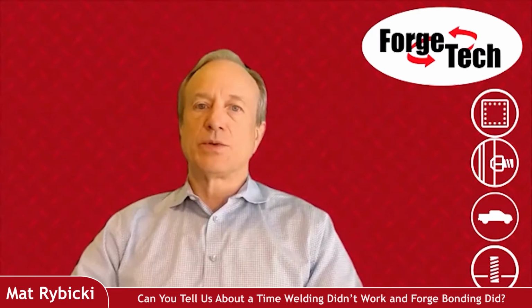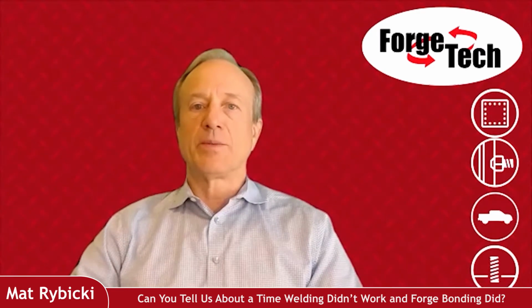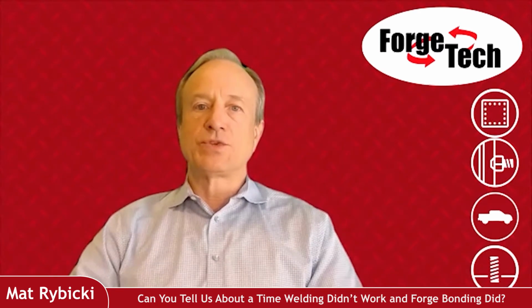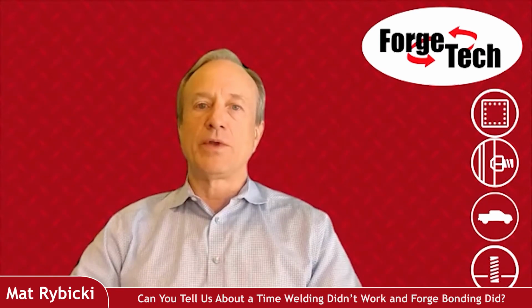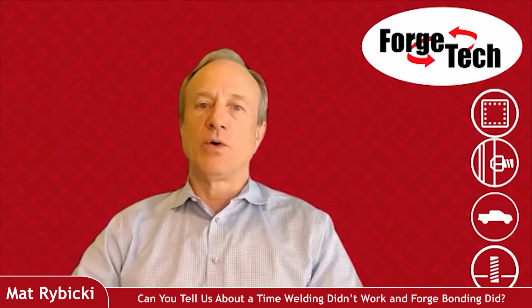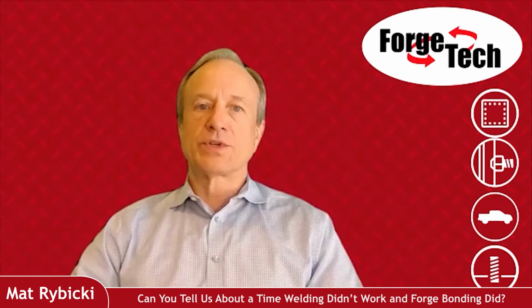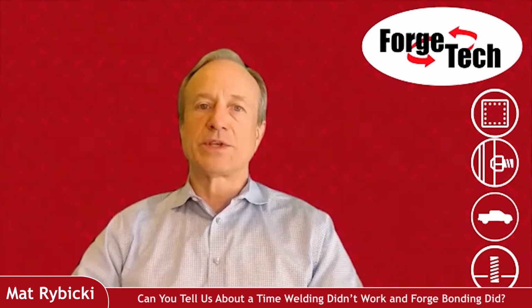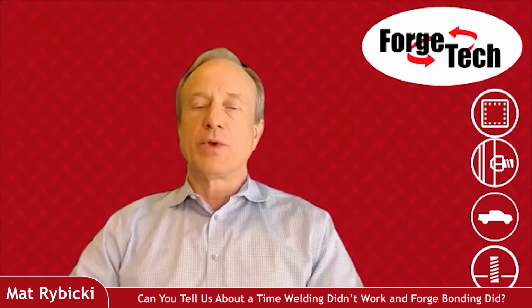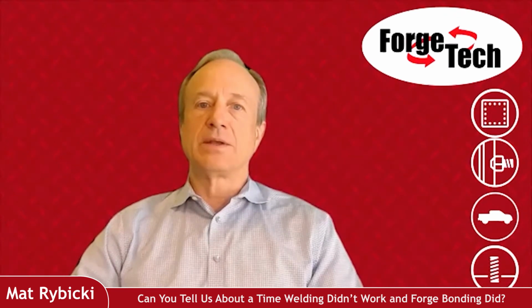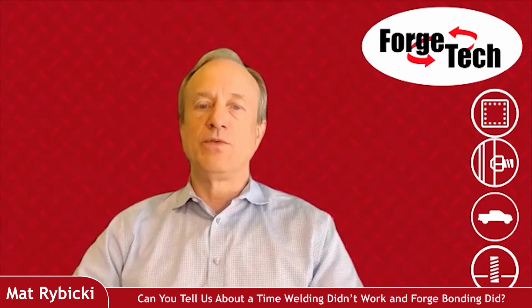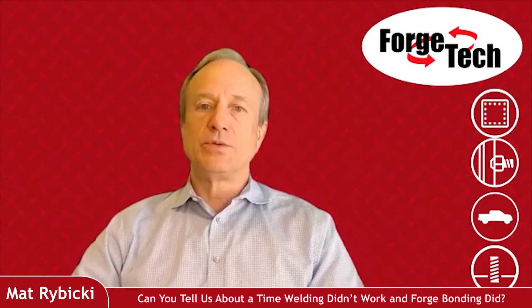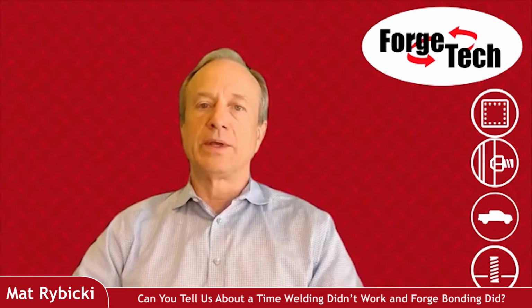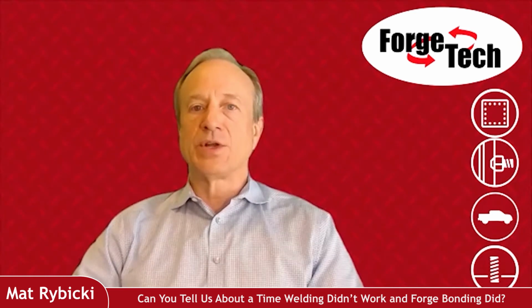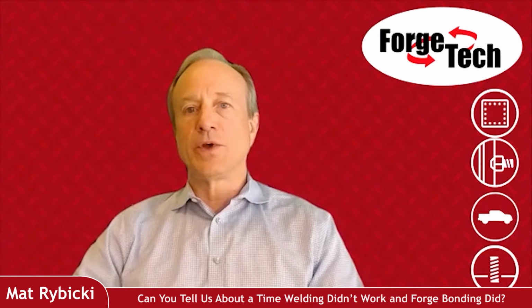But there were problems with that. One is that the welders were working from a man lift, and it was windy, and so the man lift was moving while they were trying to lay a nice bead on a vertical surface. Arc welding works quite well on a flat surface, but on a vertical surface, a skilled welder can still do a good job. But throw into it that the man lift basket they're standing in is moving around, and they were unable to perform a good quality weld. So when it came time for a weld inspection, the welds failed the inspection. So they had to remove those brackets and try again.